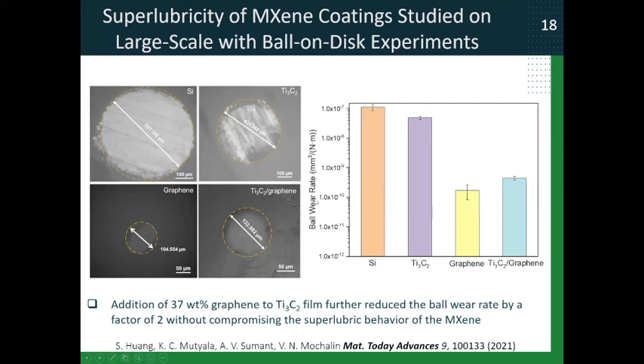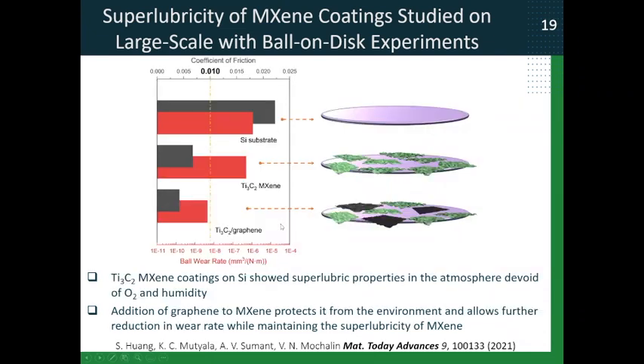Ball wear rate. MXene itself shows this value, but when we add graphene to it, the value becomes much less. And importantly, we still maintain the superlubric behavior offered by MXene. Graphene itself did not show superlubric behavior in these experiments, but when we coated graphene on the MXene film, we achieved both superlubric behavior due to MXene and very low wear rate due to graphene. So we observed, again, superlubric properties in the atmosphere devoid of oxygen and humidity, and addition of graphene also protected the MXene film and reduced ball wear rate.